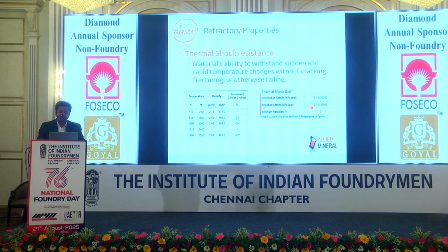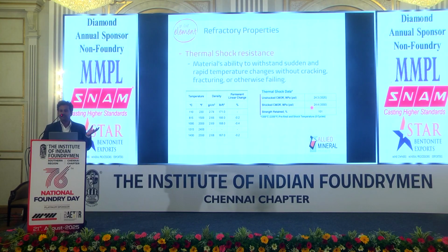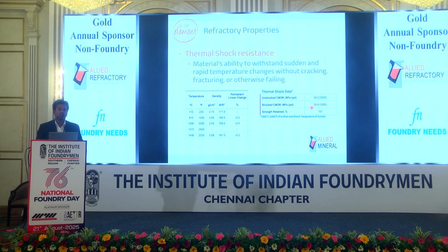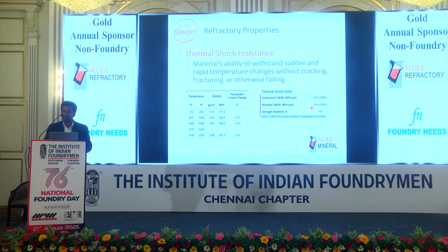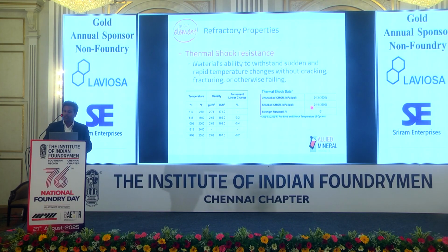Thermal shock resistance is the first and foremost important property of your ladle refractory. When you consider the induction furnace, as soon as you tap out the metal, it is always in hot condition. Whereas in the ladle, you will be transferring the metal and the ladle will be idle, exposed to the atmosphere. There is an enormous amount of thermal shock involved compared to the induction furnace. So our refractory should have more thermal shock resistance. Thermal shock resistance is the ability to withstand sudden and rapid temperature change without cracking or failing.